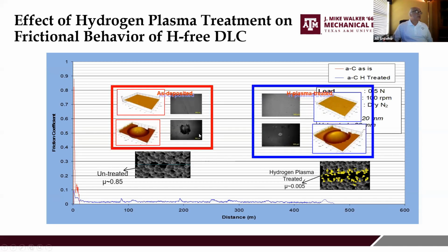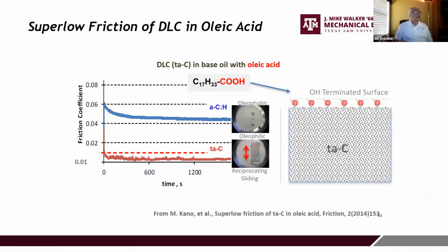And of course, this also reflected very well on the wear of these materials. In the case of non-hydrogenated or untreated surfaces, the DLC film actually wore out very quickly. In the other case, the plasma hydrogen-treated surface, you could hardly see where the sliding had taken place. So extremely low friction coefficient also resulted in almost zero wear.